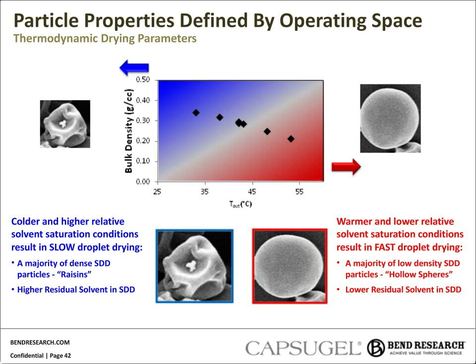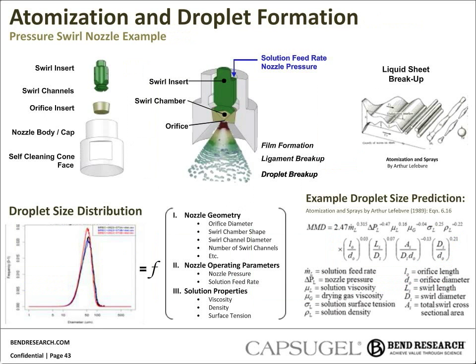So switching now to the droplet formation or atomization parameters, a pressure swirl nozzle is shown on this slide. There are many different types of atomizers that can be used in the spray drying process: two-fluid, rotary, all different types. The pressure swirl nozzle is preferred for SDD manufacture just due to its ease of use and robustness of operation. It also generates really pretty narrow droplet size distributions and is readily scalable.